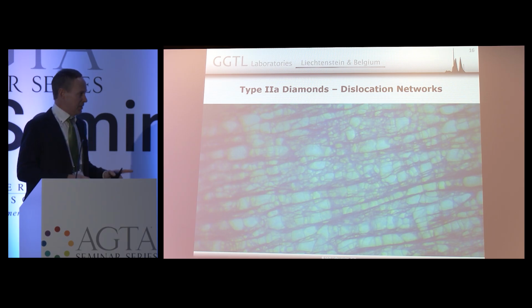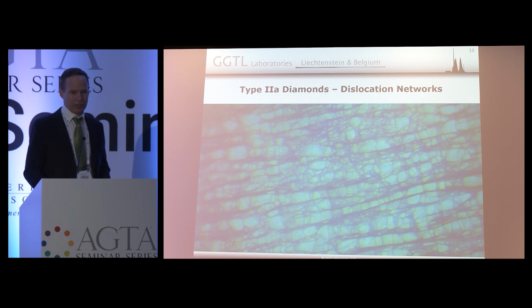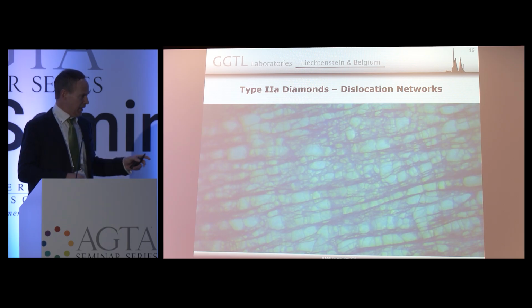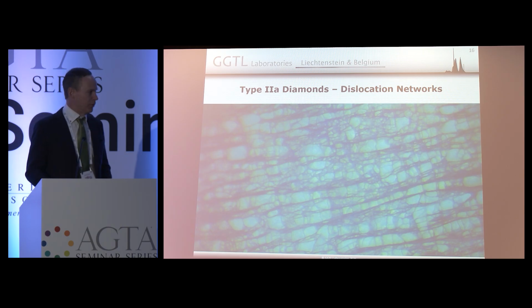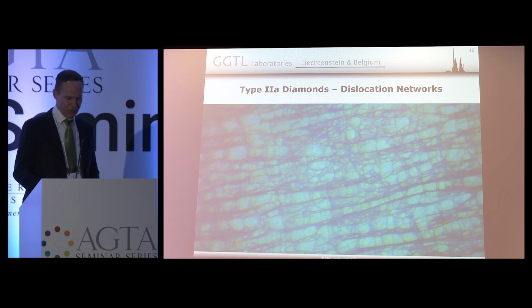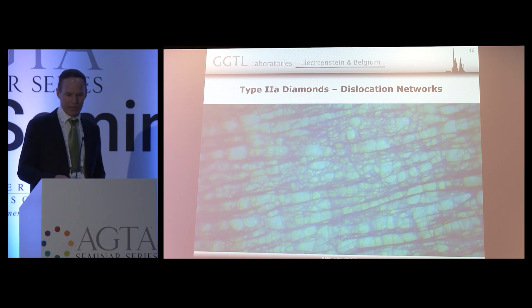You don't see this exactly like that in synthetics. Some synthetics may show, let's say, similar features, but they are distinct from the typical dislocation networks we see in natural type 2A diamond. They happen because, curiously, the less nitrogen you have in a diamond, the more easily it is plastically deformed. So you get all those dislocations in huge numbers, much more so than in nitrogen-rich diamonds.